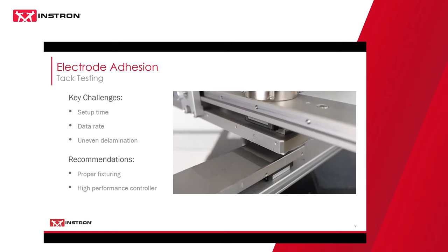So another challenge that comes from tack testing is the data rate. Data rate's not always considered when running tests like this, or even in general. In a lot of battery tests, especially separator film and foil and 90, 180 degree peel testing, data rate isn't super critical. You don't need a very high data rate. But when we talk about a tack test, the force is generally occurring in less than a second, usually even less than a quarter of a second, where you see the peak of the force come in.